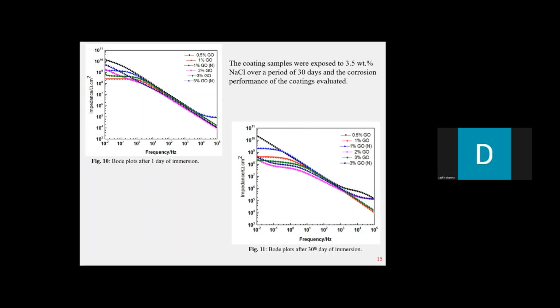So this clearly indicated, and was also in line with previously reported literature, that a smaller content of nanoparticles is much more favorable because it can uniformly disperse within the polymer matrix. However, the lowest performance was exhibited by the red one, which was the 1% GO fabricated without the influence of vacuum. And the second lowest, which was expected, was exhibited by the 3 weight percentage GO. So in other words, the green and the red, which were 1% and 3% GO, exhibited the lowest results. And this was as expected because they were fabricated without the influence of vacuum, and they also exhibited the lowest water contact angle results.